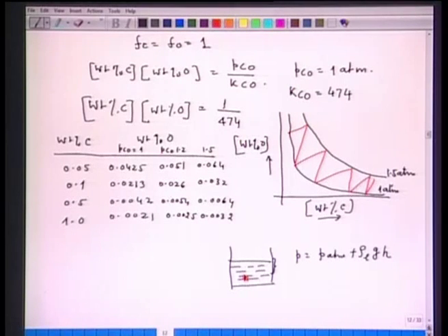So, if the nucleation of C plus O equal to CO bubble occurs deep in the bath, then on account of the ferrostatic pressure plus atmospheric pressure that this bubble experiences, the dissolution of oxygen in the bath increases.